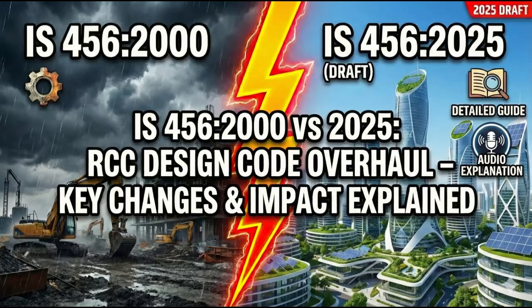That's the argument. The second, more damaging critique relates to the practical difference this level of detail makes in the final constructible design. When you compare the calculated moment of resistance using the old constant strain values versus the new 5-digit computed values, the difference for common grades like M40 is often marginal, perhaps 5% to 15%. Which doesn't sound like a lot. It's not. In a design office, you don't design a beam for 103 kilonewtons. You group members and size them to 125 kilonewtons for simplicity and constructability. So the practical constraints of construction, using standard bar sizes, grouping similar members, making detailing convenient already, swallow up that 5% to 15% theoretical gain in accuracy.